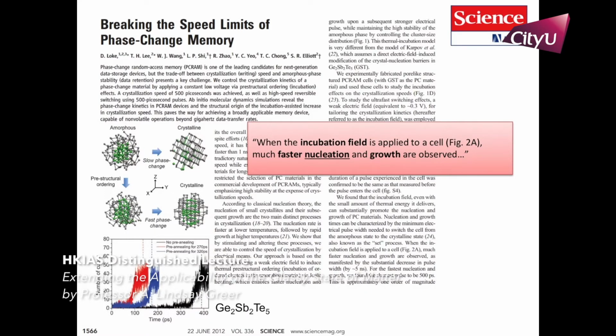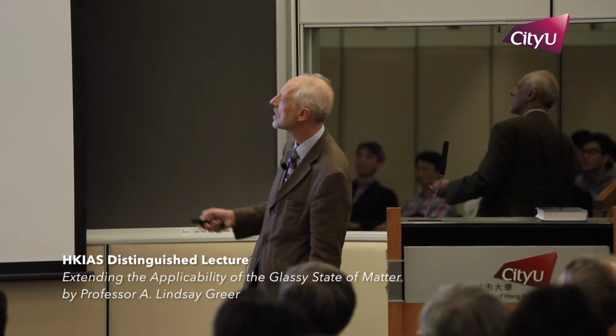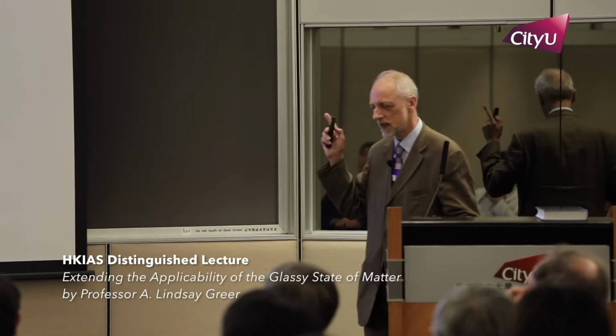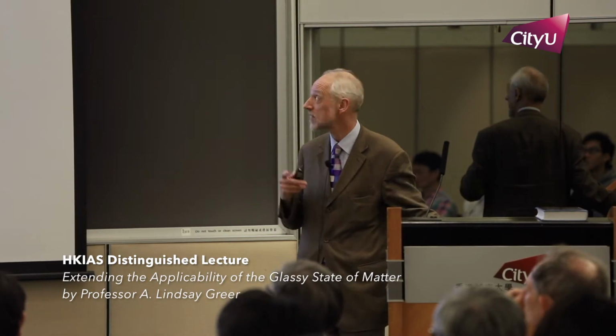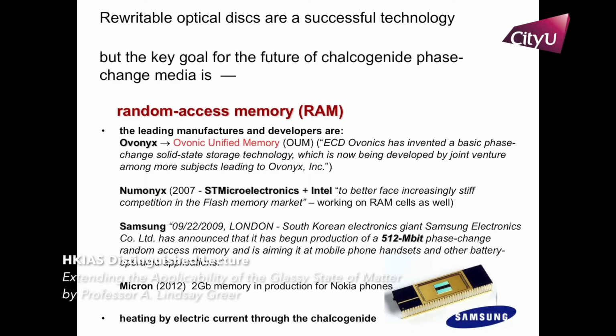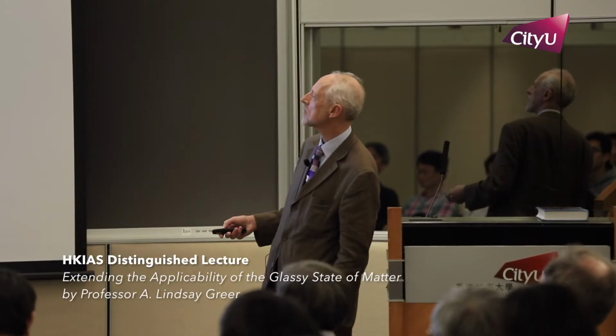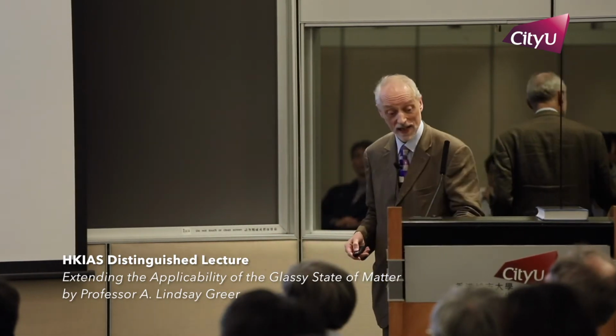And you can speed it up a bit by seeding it with little crystals, and they're now down to about 500 picoseconds switching time in optimized systems. So the key thing for speed here is to understand the crystallization. Various device implementations over the years. This is one from Intel and Micron. They're making the points about it being non-volatile, 1,000 times faster than other systems, 10 times denser memory capacity than conventional stuff, and so on and so on. So this continues to advance as a technology.